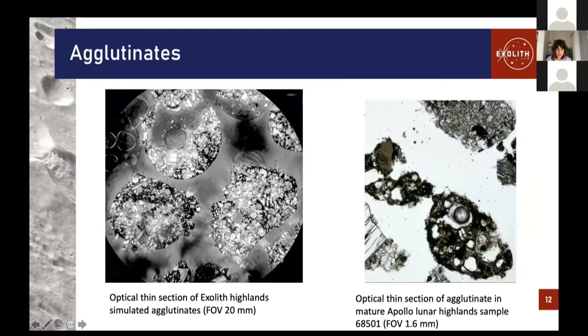This on the left here is an optical thin section image, in reflected light. This is one of our agglutinates, or several of our agglutinates, of Highlands composition. The dark material here is the glassy matrix. There are some air bubbles in there, and then there are particles, mostly anorthosite, from the lunar simulant. And just for reference, here's a picture of a Highlands agglutinate from an Apollo sample.